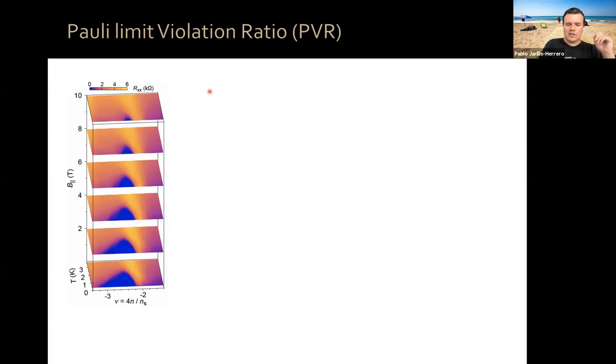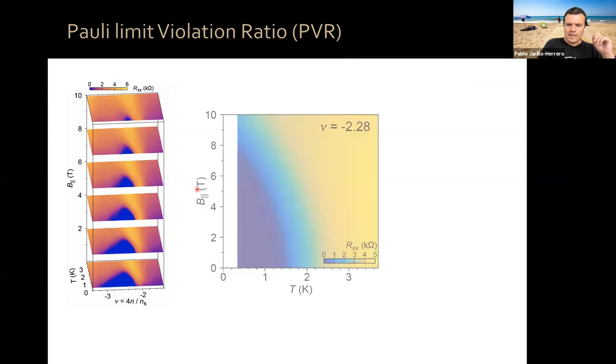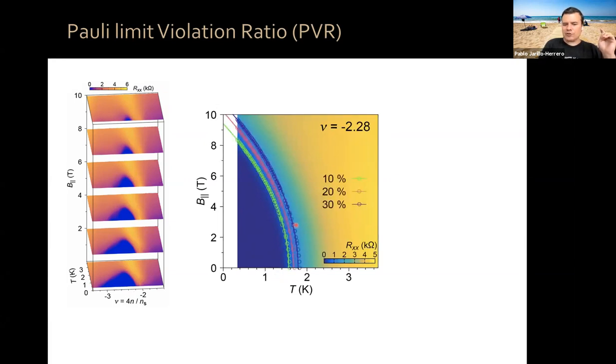superconducting dome, okay? So now what we can do to do this continuously is pick a particular density and do temperature dependence and parallel magnetic field dependence continuously. Here, dark blue means below, essentially, TBKT or less, so dark blue means zero resistance. We can see this profile. So we can take any threshold that we want for TC: 10% of the normal state resistance, 20%, 30%. We can take TBKT, 50%. They all give the same result, okay?